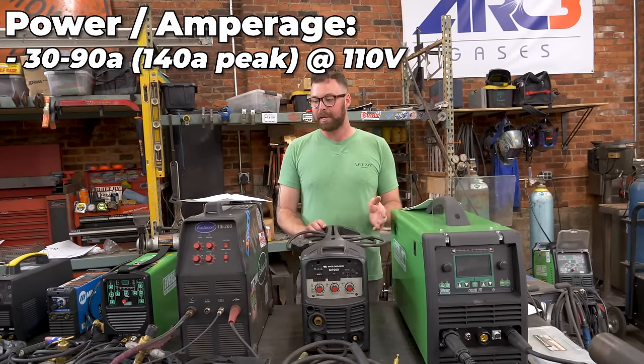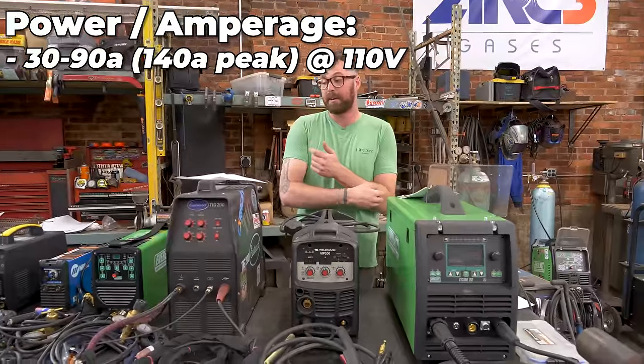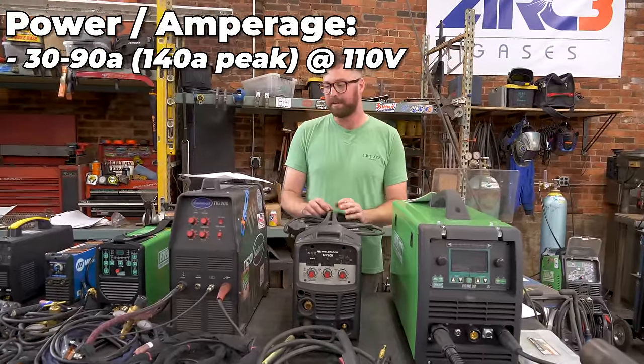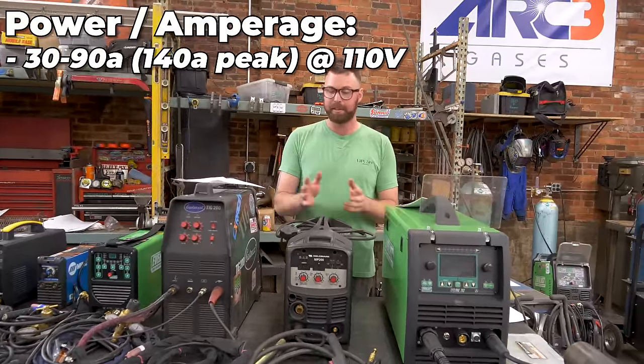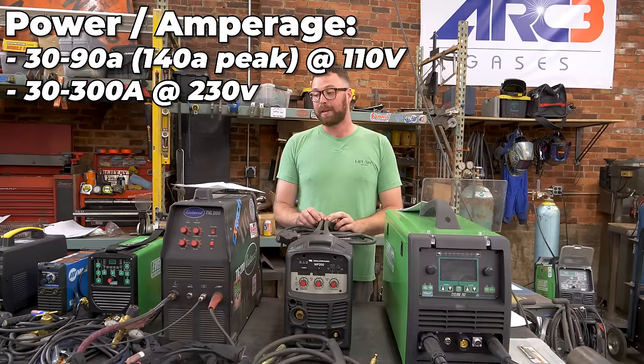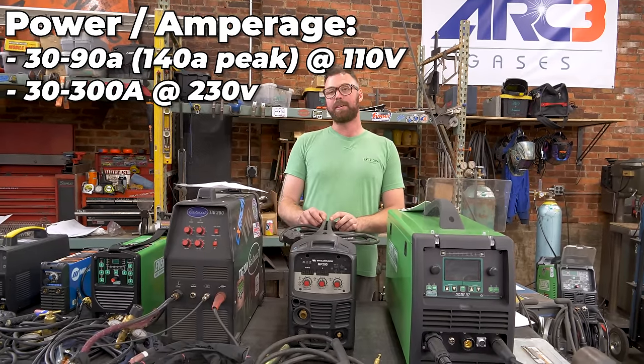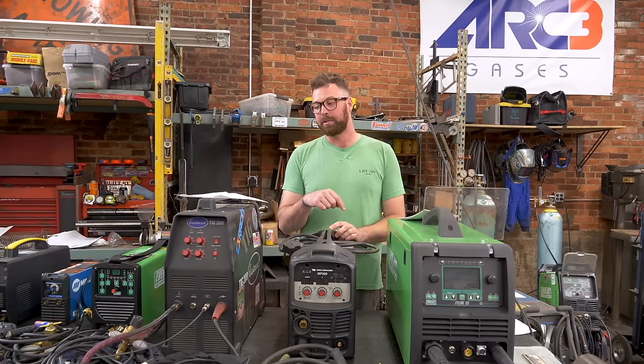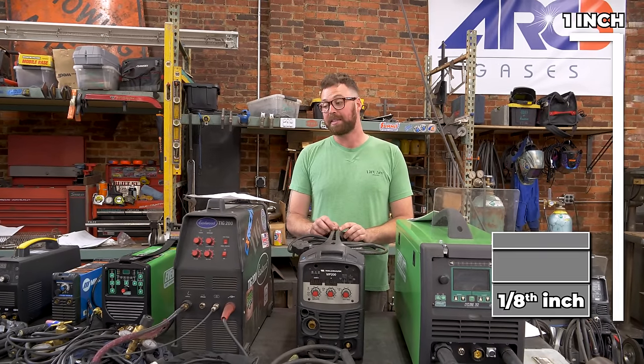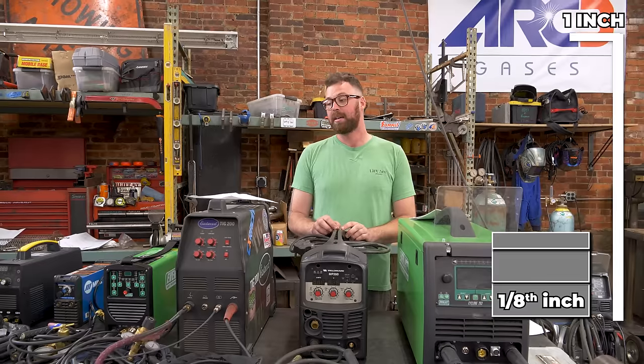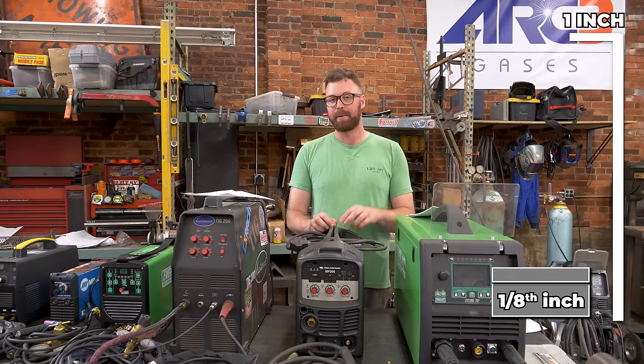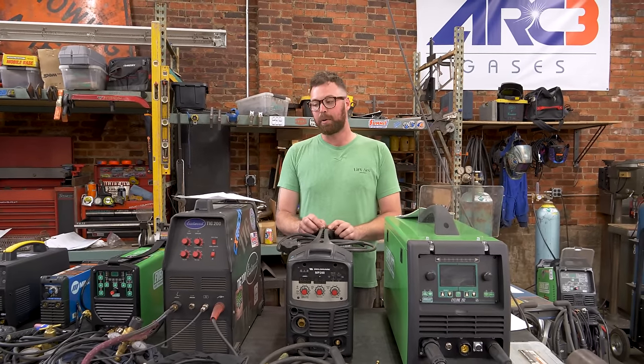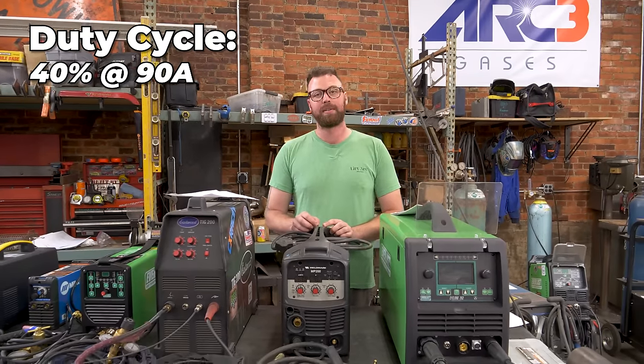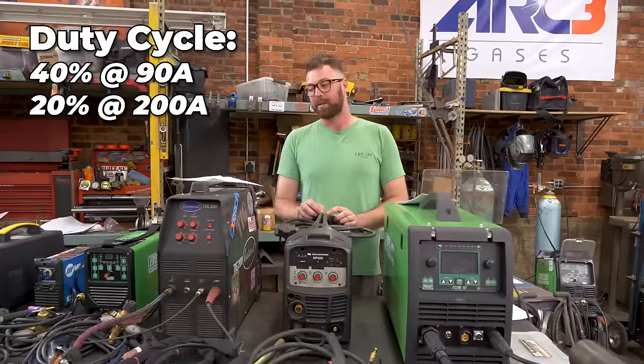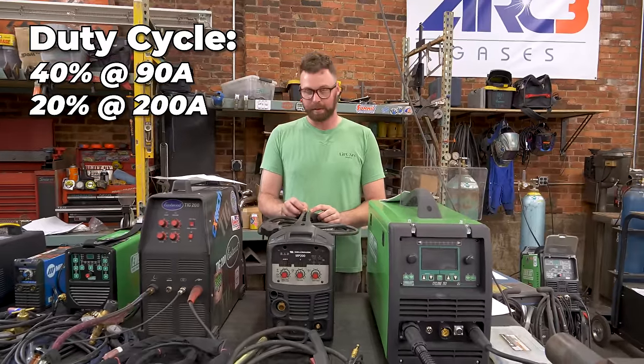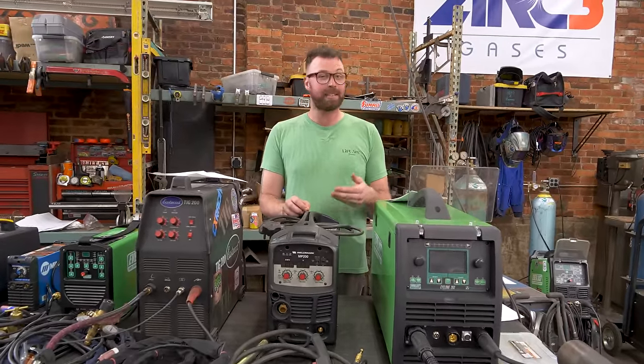It has a 30 to 90 amp range with a 140 amp peak at 110 volts. It's a multi-voltage welder, 110 and 220, and a 30 to 300 amp rating at 230 volts. And on 220 volts, it can MIG weld 5/16 steel on a single pass and 3/16 steel on a single pass on 110. Duty cycle is 40% at 90 amps on 120 volts and 20% at 200 amps on 220 volts. So this thing's got some chops.